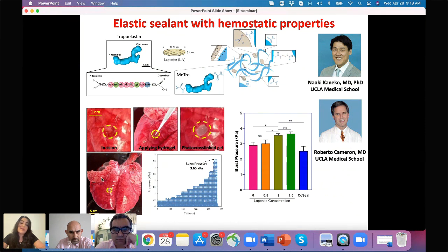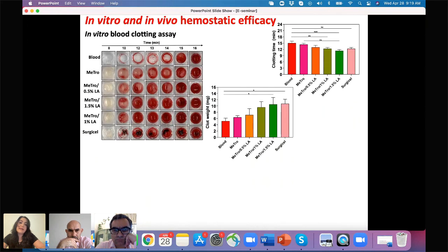Before we move on to the in vivo test, we set up an ex vivo test where we use explanted porcine lung, and then we create a larger size defect, apply our biomaterials, and connect the lung to the ventilator to measure the burst pressure. And here are some preliminary data showing that as we introduce laponite in our hydrogel, the burst pressure improved, and also the burst pressure for the laponite combined with MeTro was higher than CoSeal. We next test the efficacy of these biomaterials for blood coagulation.